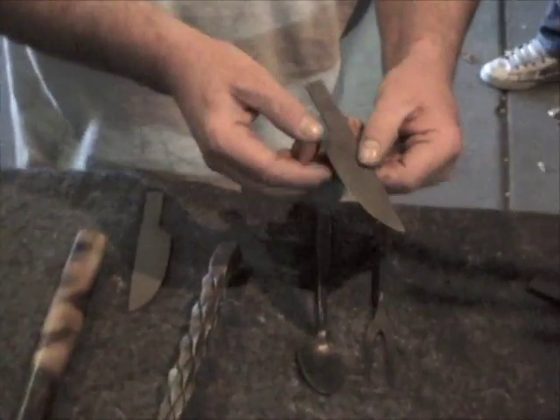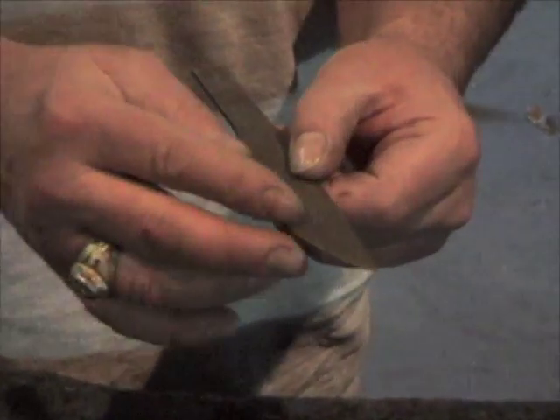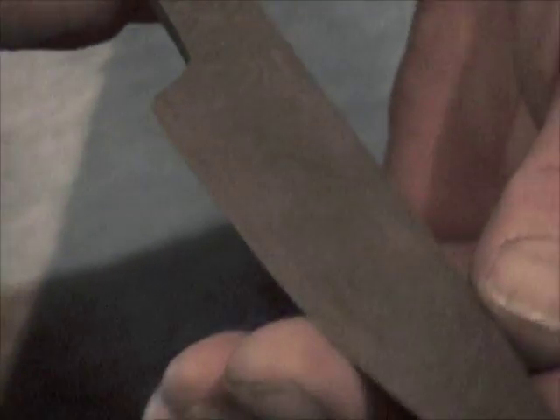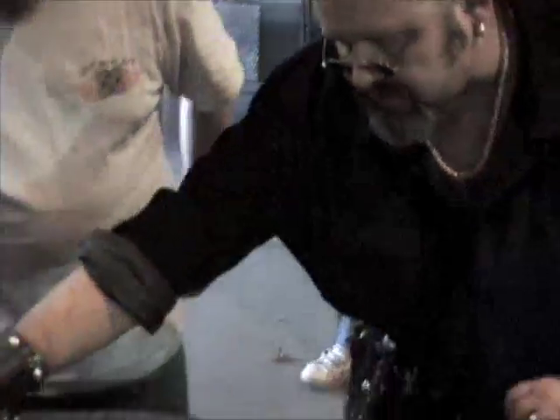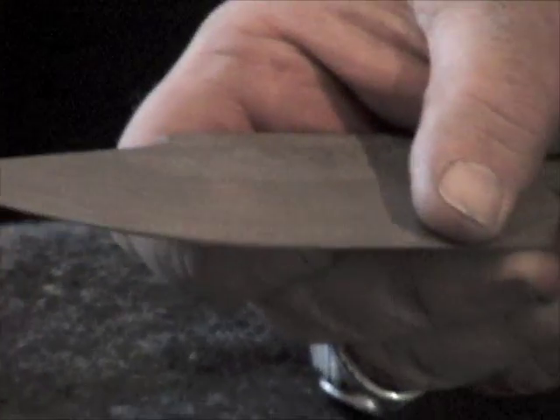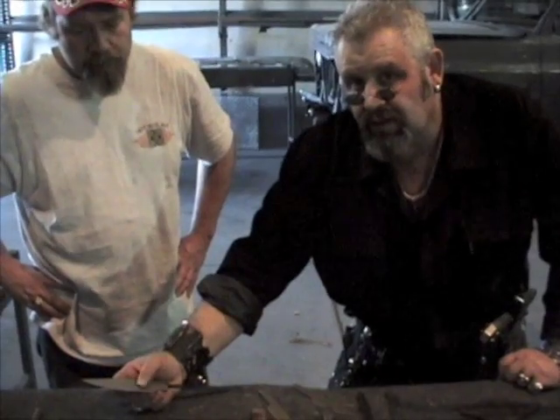When you get really thin down at the edge, it's almost like a microscopic serrated edge because you've got both steels coming together in a lot of areas — you can't see it because it's microscopic. The metal is sandwiched in between, less than paper-thin each layer. One thing nice about Damascus — it's a fine serration. When you cut with the Damascus, the L6 and the 1080, the one that's a little bit weaker flakes away and the harder steel stays, so it sharpens itself to a certain extent when you're cutting with it.